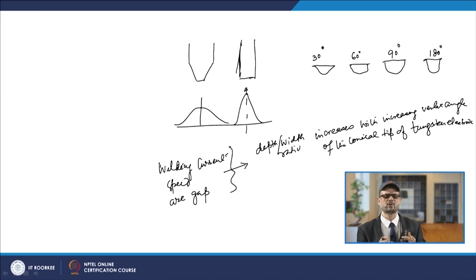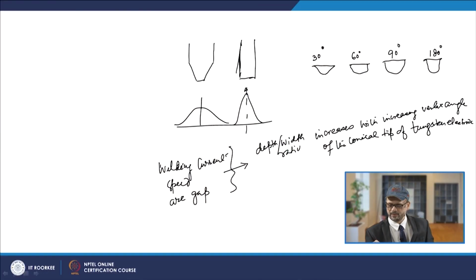We discussed this because we should have an idea about how this power distribution varies, and how the tip geometry will be affecting the arc welds. As we see, if you increase the vertex angle, the depth to width ratio will be increasing. So, in this case the depth is increasing as the vertex angle is increased, and it has also been reported by another researcher, Key. He has also seen, with arc welding, a similar phenomenon.